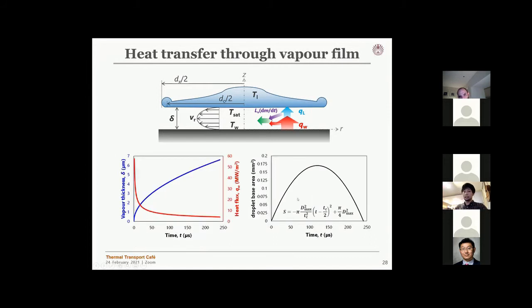This is the sum of the calculations we've done. On the left-hand side, we plot the vapor thickness as a function of time, and from the vapor thickness we can also calculate the heat flux as a function of time, which should look like this. To get the amount of heat taken by the droplet, we have to multiply this heat flux by the droplet base area, which is the heat transfer area.